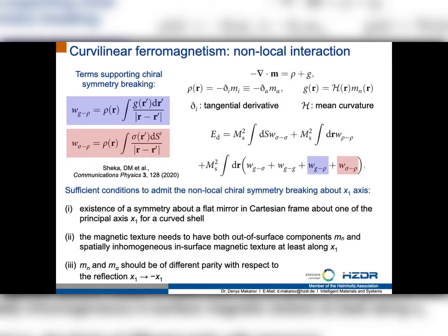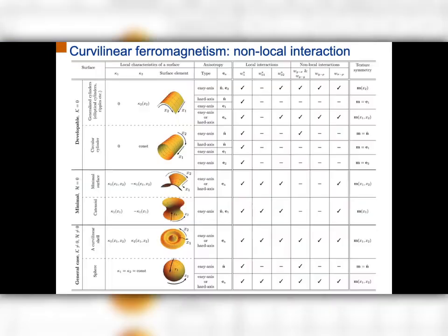And we were able to derive only sufficient conditions, which, for example, consider the symmetry of the geometry, the symmetry of the texture, and also the different parity of the texture with respect to the reflection, like mirror planes. And in this case, you can at least predict that a given system will have the chiral symmetry break due to this non-local interaction, which comes from magnetostatics, but not from, let's say, standard spin-orbit interactions which you have in the system.